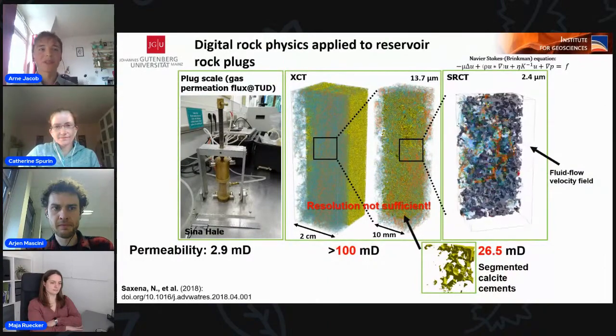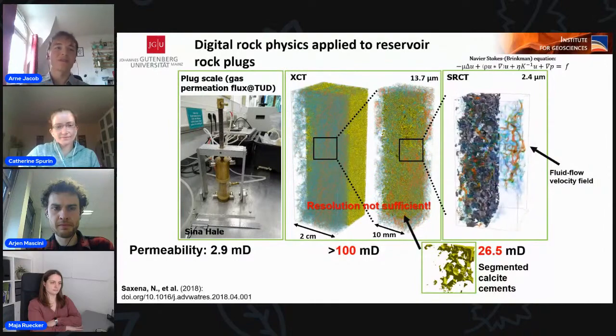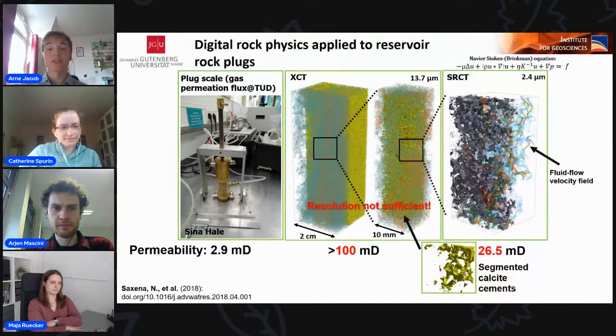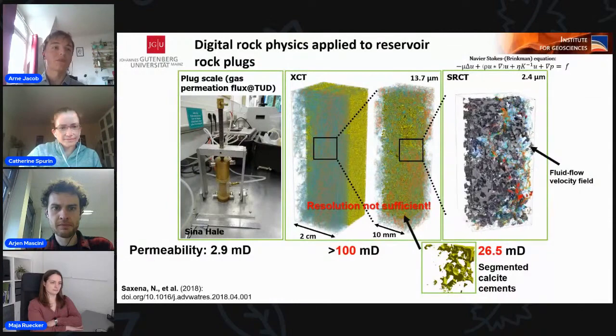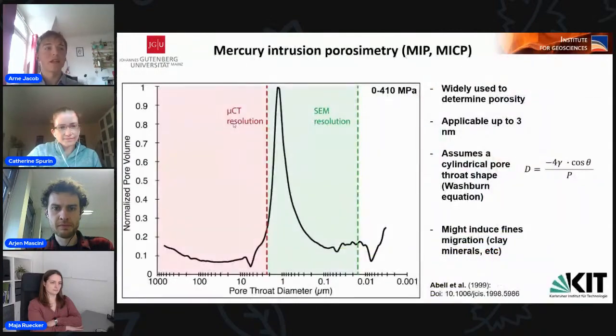So the upcoming question was, why is the permeability of the samples imaged by a synchrotron still too high compared to the experiments? Well, we did mercury intrusion porosimetry to determine the pore size distribution in our samples. This method is widely used to determine pore size distribution of a sample from micrometer to nanometer scale. The technique relies on the Washburn equation, where the pore throats are assumed to have a cylindrical shape.